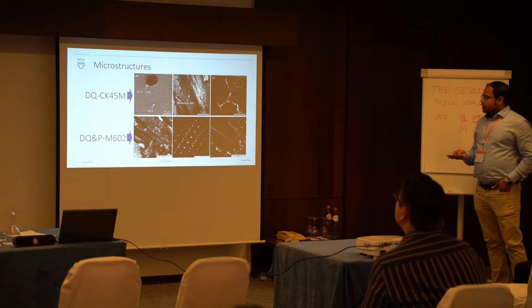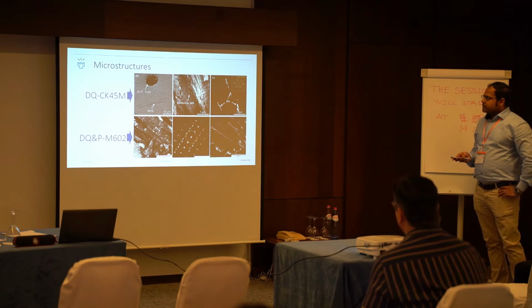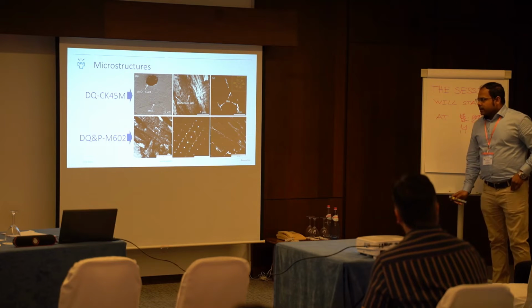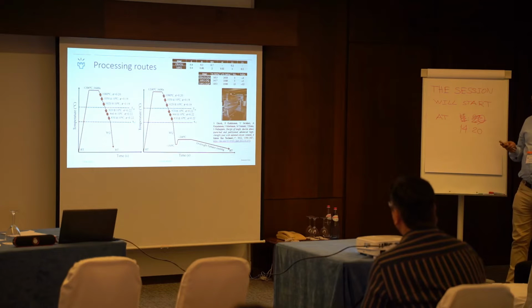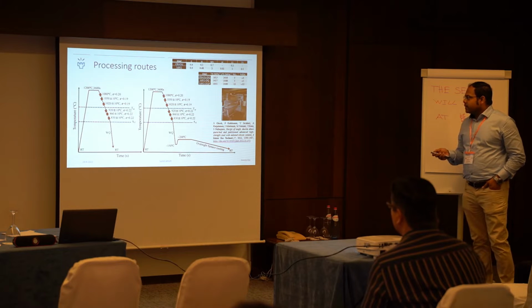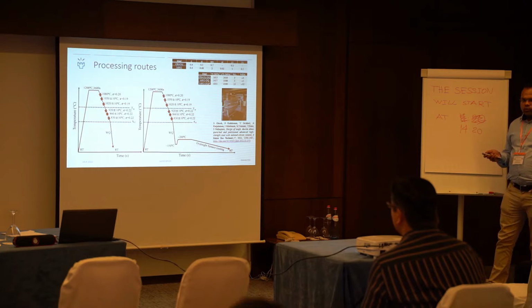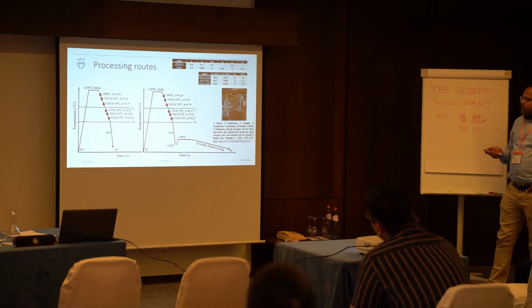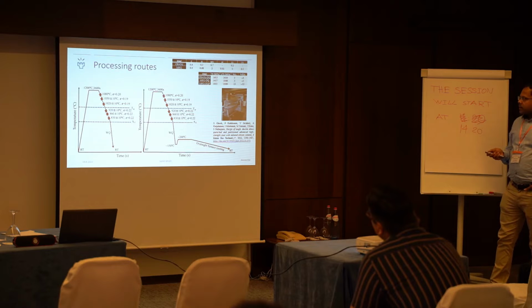And of course the mechanical properties have also been investigated. In the case of the direct quench variant, CK45M steel, the yield strength was in the range of 1600 megapascal and UTS was more than 2 gigapascal, in the range of 2400. Of course, the ductility level was quite poor and the retained austenite fraction was around 4%. Whereas in the case of the DQ&P variant, it has a yield level in the range of 1000 MPa together with around 2 gigapascal UTS and 13% elongation, and the retained austenite content was around 12%.